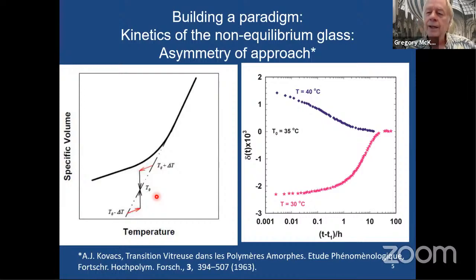but the fictive temperature in this regime is greater than the temperature of test. Or rather, the temperature of test is greater than the fictive temperature. And when that's the case, then you're going to be in a condition where the relaxation times are longer than the equilibrium times. So that's a very important idea that you should hang on to when I talk later about the ultra-aged glasses.